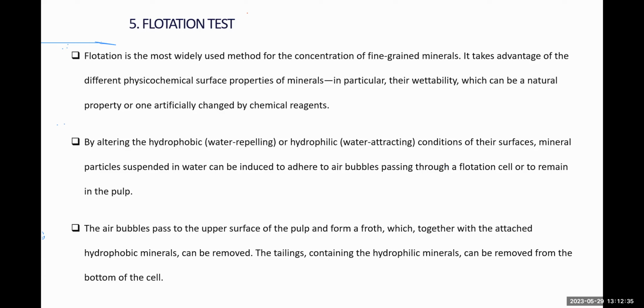It's very important, but this flotation process is not efficient if your grinding process was not optimally done. If your grinding process was not done properly, if you did not get the right feed size into the flotation cell, the materials will not float. Because for materials to float, they must have a high degree of buoyancy, so that with a little blow of air, maybe the air comes in pneumatically from the system, or it can be inbuilt in the flotation cell, and with the addition of chemicals, activators, the lithium ore is able to float easily without much trouble.